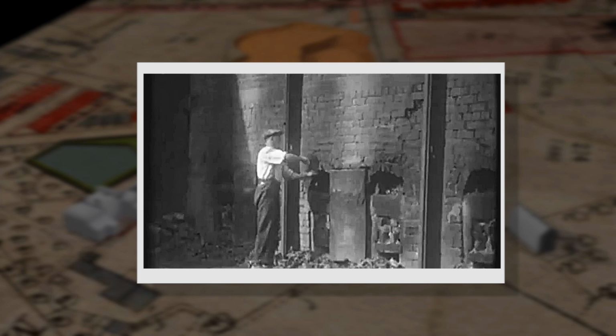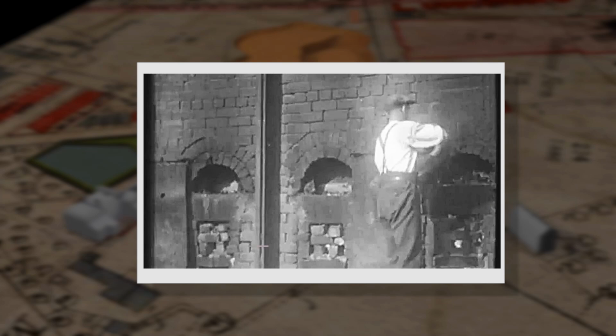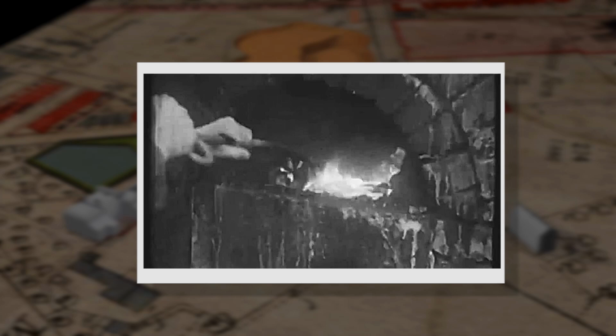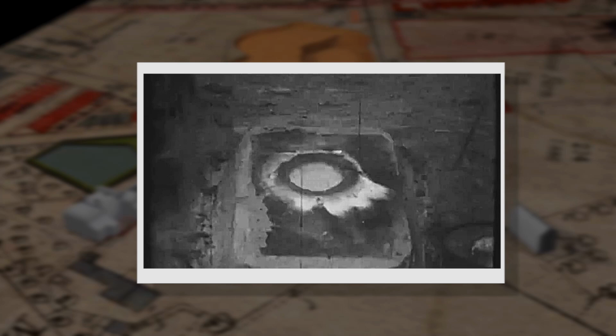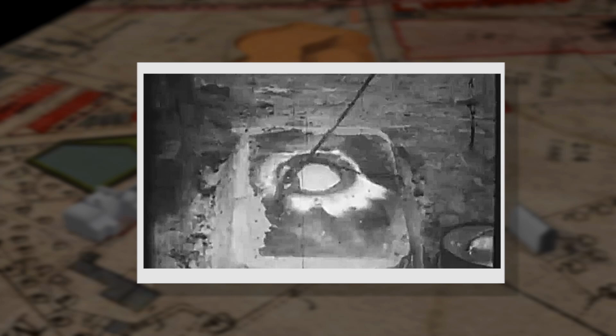The firing may take several days, but the kiln will be constantly monitored, fed with coal fuel, and a constant high temperature maintained. At various stages, common salt will be added to the kiln. Sodium from the salt reacts with the silica in the clay to form a glassy coating of sodium silicate. Now this glaze may be coloured various shades of brown by using iron oxide, or blue by using cobalt oxide, or purple from manganese oxide.